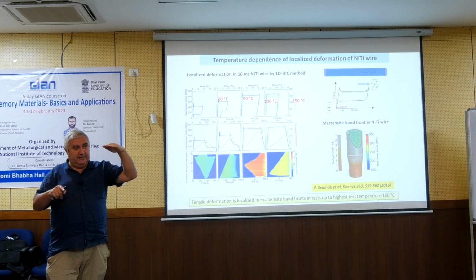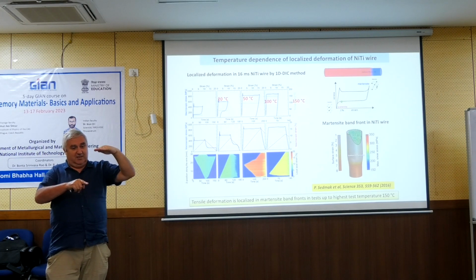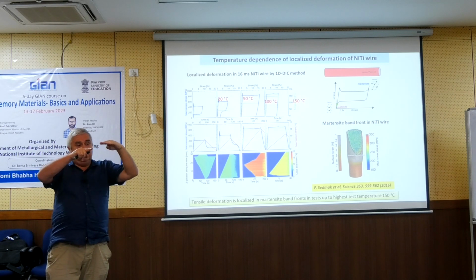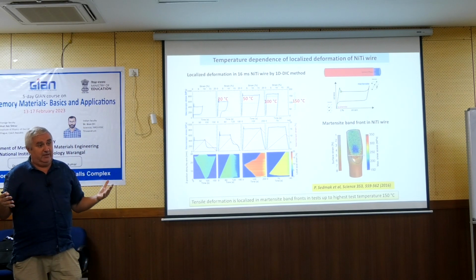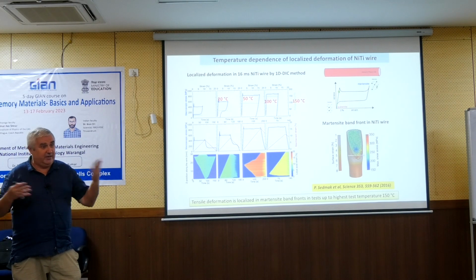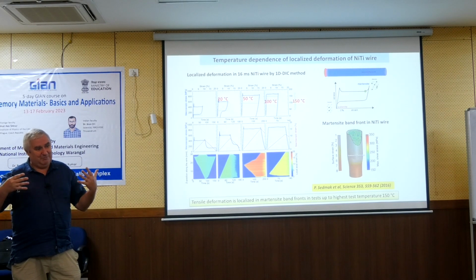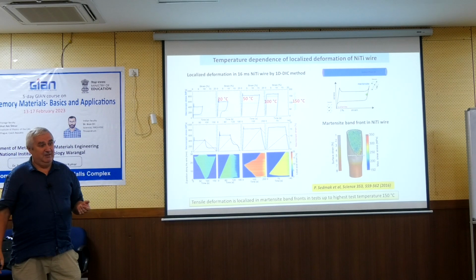So if you are cooling under the constant force, you are cooling with some rate, but you don't control the rate of the transformation. And then suddenly the transformation starts and proceeds extremely quickly. So we are doing experiments in which we do not control the strain rate. In engineering, if you have strain rate dependent deformation processes, this would be a criminal act. You have to control the constant strain, but we don't care in the shape memory field. So this is some indirect confirmation that in the first approximation it is rate insensitive.